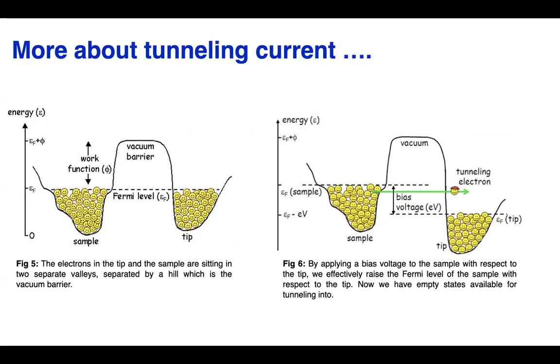Okay. More about the tunneling current, because the tunneling current plays a very important role during the scanning process. Look at figure 5. I like this figure because it explains this well. You can see this happy face indicates electrons in the tip and the sample sitting in 2 energy valleys. When we don't have any bias voltage, the Fermi levels of the sample and the tip are at the same level, so electrons on either side don't see any empty states. So there's no tunneling between the sample and the tip.